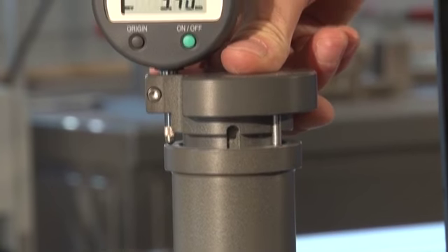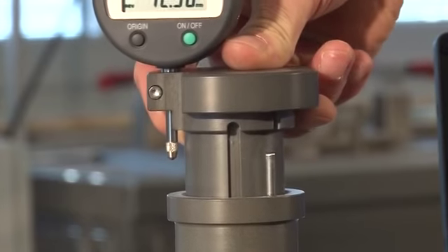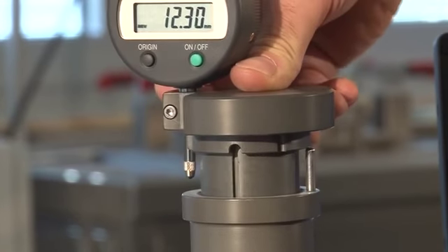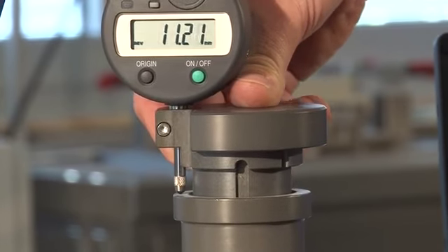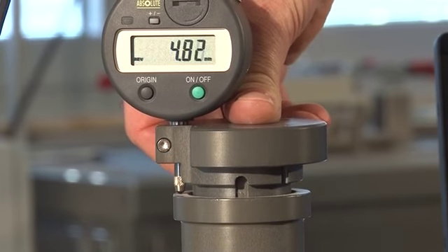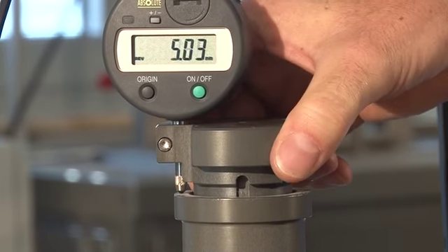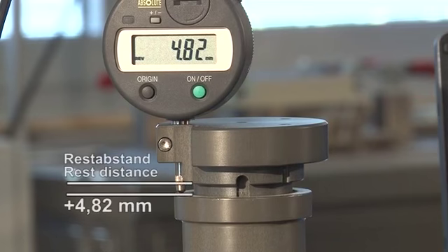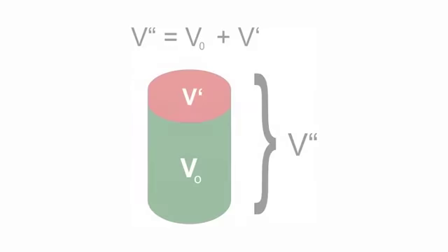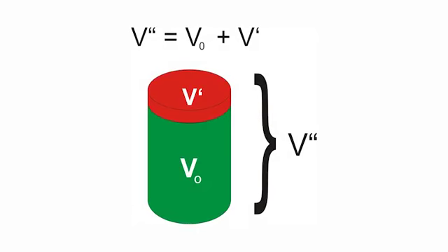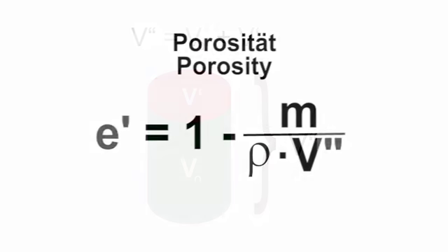In this example, the remaining distance of the sample is 4.82 millimeters due to too much sample weight as a result of incorrectly assumed porosity. However, a new cement bed does not need to be prepared. The additional volume V prime is calculated and the old volume is imputed so that V double prime is the result. The actual porosity can be determined with equation e prime.